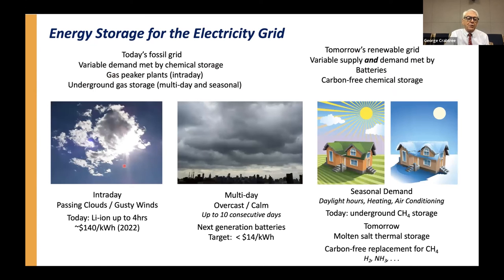So what are the applications? Well, intraday, passing clouds, you can reduce the output of solar panels by 70% while the cloud passes over. Clearly, you need a battery, and it could be lithium ion, that takes care of the seconds to hours variations. Cost of lithium ion now is about $140 a kilowatt hour, but that won't work for multi-day overcast or calm days. Maybe historically 10 consecutive days in a row, it happens fairly frequently. You may need the next generation battery, and DOE has already established a target for that. Get the cost down by a factor of 10. So it's got to come down to $14 a kilowatt hour. Big challenge, although there are opportunities there.